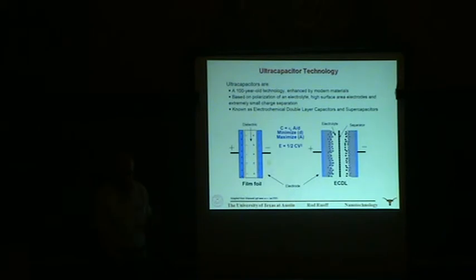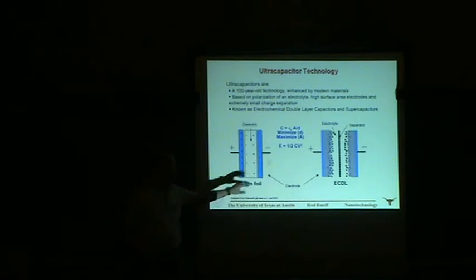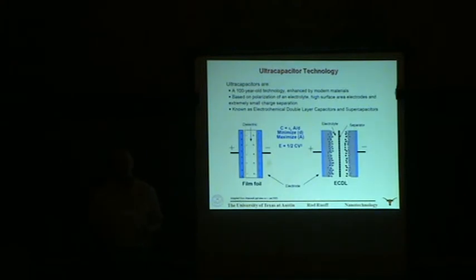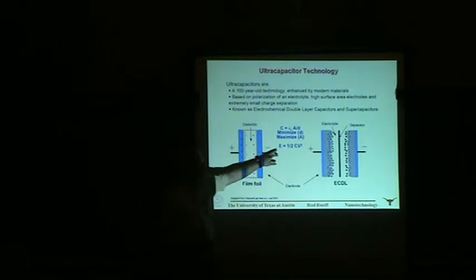So this is called an electrochemical double layer capacitor. Notice that the energy density is proportional to the voltage squared. So maybe graphene, compared to the current carbons that are used, will also allow using new electrolytes like ionic liquids that operate at much larger electrochemical windows, larger voltages. And those larger voltages could also allow higher energy densities as long as the system is stable.